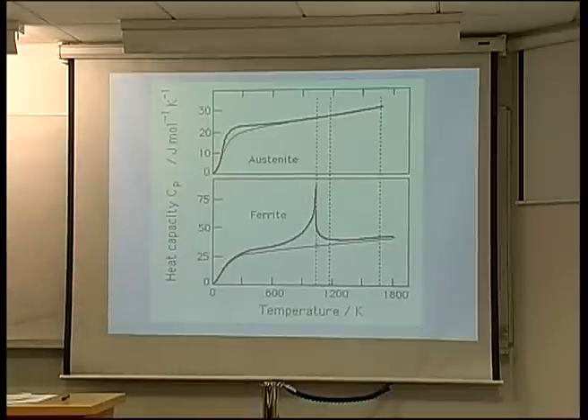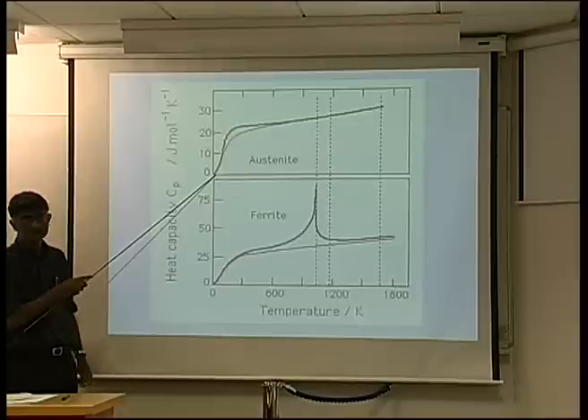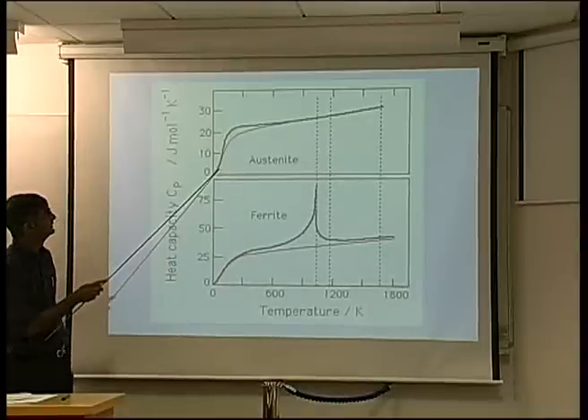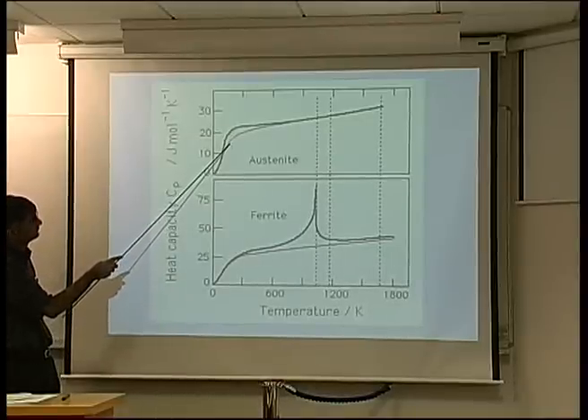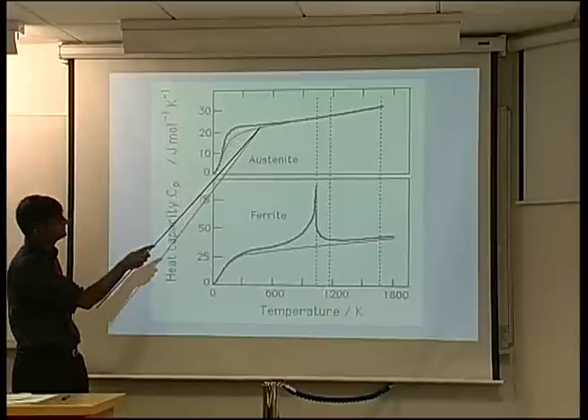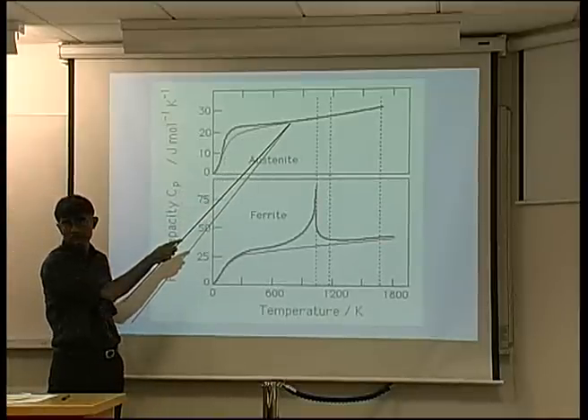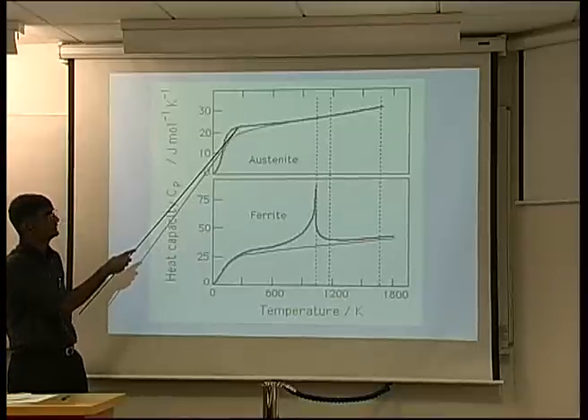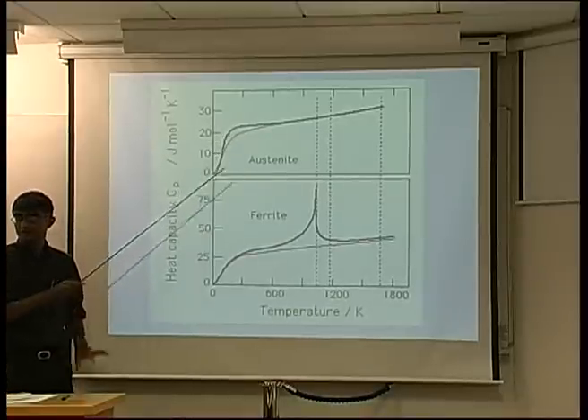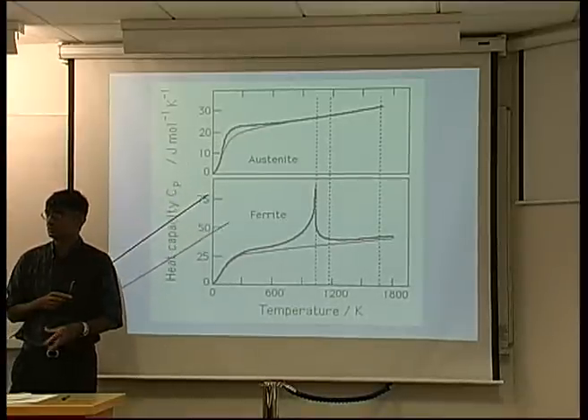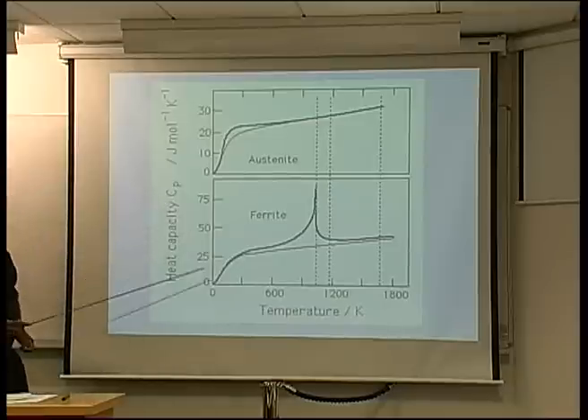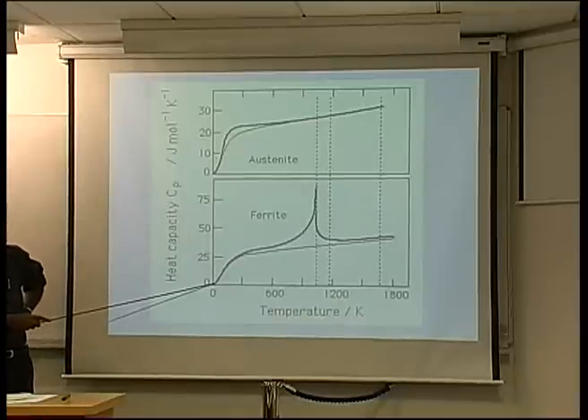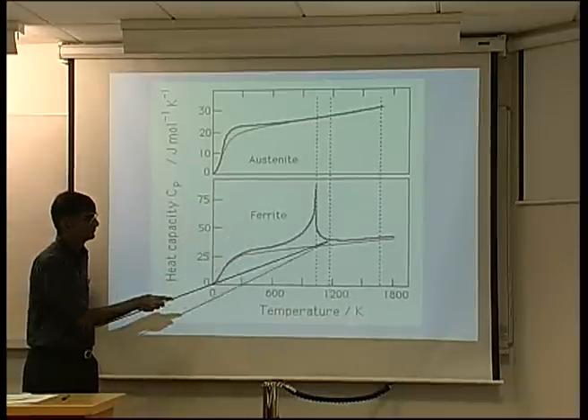This is to show you the difference between just the vibrations of atoms and other terms coming in. So this is the cubic F form of iron. If it was just a question of lattice vibrations, then this would be the heat capacity as a function of temperature. But we also have magnetic terms here, which are giving an additional contribution to heat capacity. And in the case of body-centered cubic iron, this is very, very large.